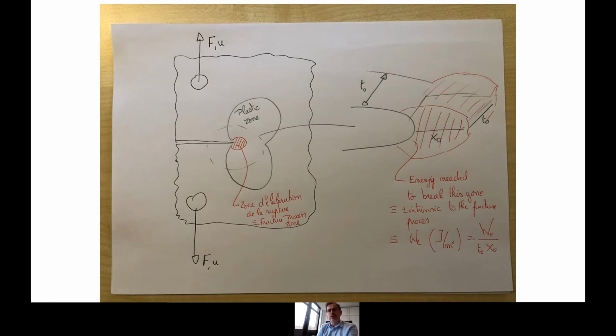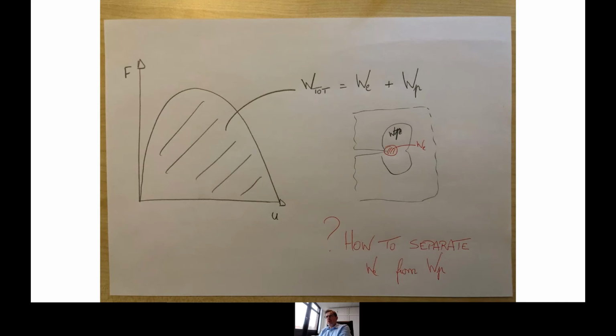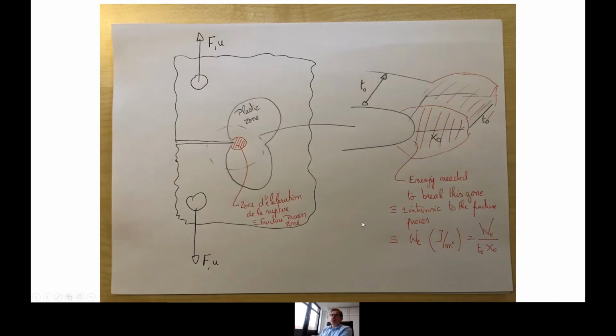The essential work of fracture basically is the work spent per unit area inside the fracture process zone during propagation, and that was already alluded to by David. So that's important. Then comes the question: what exactly is the fracture process zone? There is something in terms of physical dimensions, and something specific with thin sheets: most of the time we get crack tip necking, and that will dictate the size of the fracture process zone.